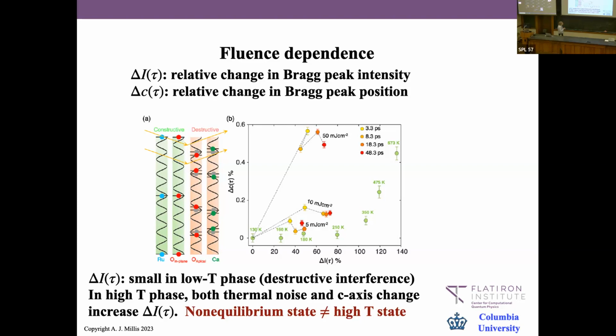The green thing is equilibrium. You go through the transition, and you see that an increase in the lattice distortion is associated with a large increase in the peak intensity, therefore a large increase in the Debye-Waller factor. With the strongly non-equilibrium probe, you see a similar increase in the lattice parameter, but much less increase in the peak intensity. So this is the argument that it's not just heating—you haven't put it into a state like the high temperature state with the same lattice constant, because you have much less destructive interference than you would in the high temperature state. It's not a proof, but it's suggestive, and that's the best I think that can be done in this class of experiments.